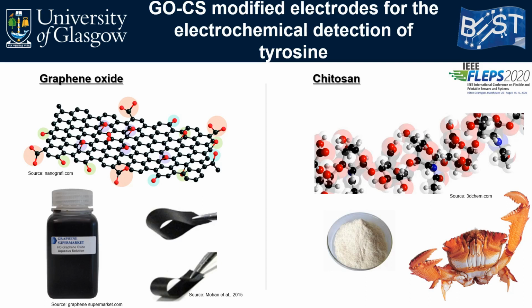The current study therefore focused on the development of a low-cost, disposable, and biocompatible electrochemical sensor for tyrosine point-of-care testing, using a graphene oxide Chitosan modified screen-printed carbon electrode, supported by a flexible polyvinyl chloride substrate. The electrochemical behavior of the graphene oxide Chitosan sensitive material that is discussed herein was assessed using both a glassy carbon electrode and the modified screen-printed carbon electrode.